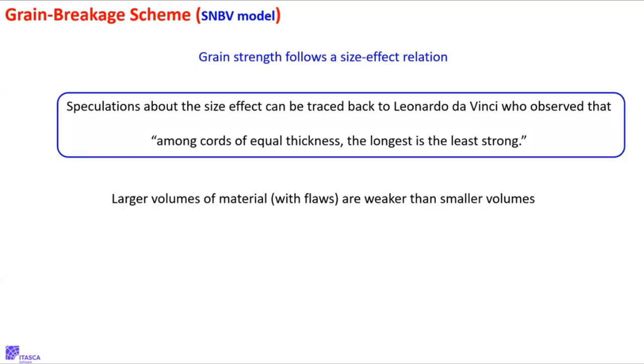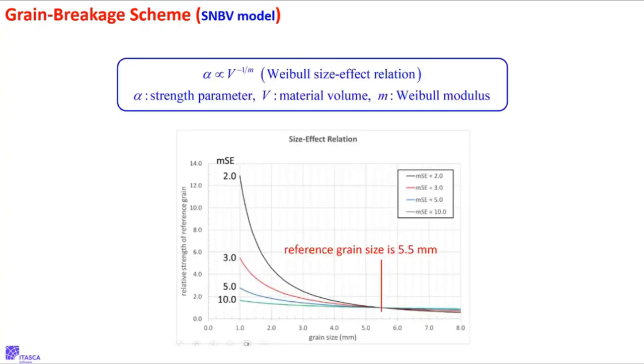Okay, and this is just mentioning the size effect business about the strength. We have to actually make our strengths follow this size effect. We have to make it so that the bigger grains are weaker. And this actually can be traced way back to Leonardo da Vinci. He took a bunch of ropes of different lengths and poured sand in a bucket underneath. And he found that the longer ropes failed sooner. The longer ones were weaker. This is the idea that if the material has flaws, the more you have, the more likely you are to encounter a critical flaw. And so this is what this crazy size effect is.